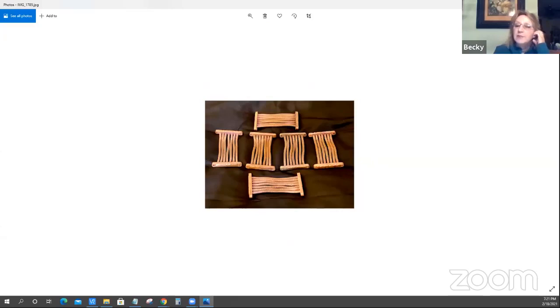Those are copper heat straps for a different code group in NASA. These are high power electric copper braid. Those braids are about 1/4 inch in diameter, and they wanted it welded, not brazed. So that is copper welding, which I did with a lot of argon, and it heats up and dissipates really fast. So it takes a while to get up to heat, and then it'll go fast. So you've got to sit on it with your arc, and then as soon as it starts melting, you have to move real fast.